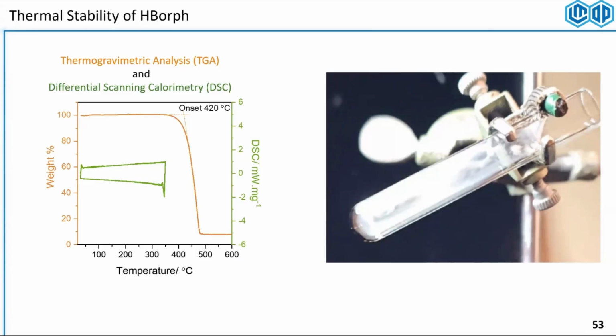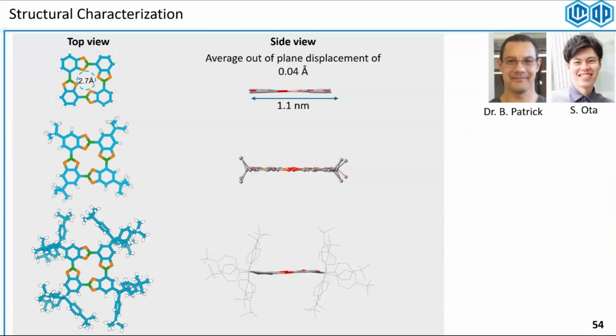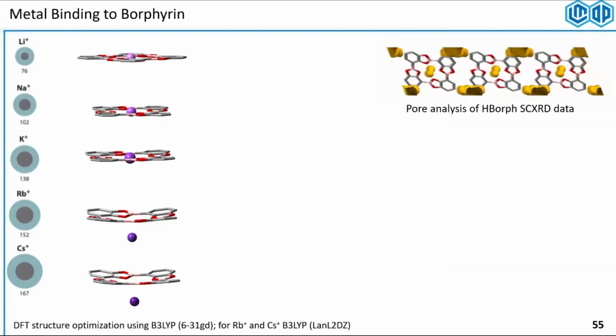I can dissolve it in chloroform and study it as a pure compound. We then crystallize it. We looked at the crystal structures to just confirm that it's really the macrocycle, and we found it's as flat as we expected. We have this nice cavity inside, and we put different derivatives, of course, to make it more soluble and easier to work with.